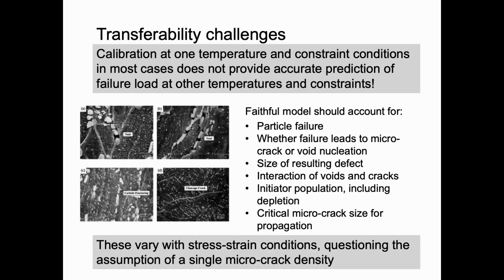The thing that we think is the problem with the existing local approaches is that all these different factors, although some of them are taken in different models, some in other models, they vary differently with stress strain conditions. That means in different locations ahead of the crack, different factors may have different contributions. And that is questioning the assumption that we have a single microcrack density curve and the entire basis of, for example, the Beremin model.